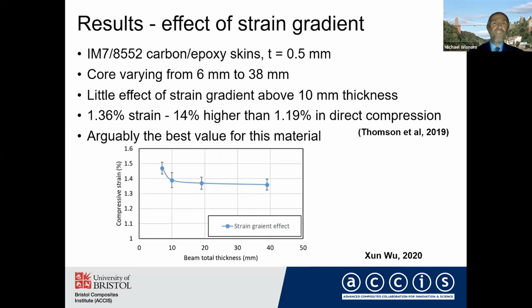What you see here for these 0.5 millimeter skins, with the core varying from 6 to 38 millimeters thick, is that at these very low levels the strain is increasing substantially. But once we get up past about 10 millimeters, there's not really very much effect. So these values here, I think, represent real compressive failure rather than an artificially high one that we get due to the suppression from the strain gradient when the specimens are thinner. That value there of 1.36% strain is about the highest value I've seen for compressive failure. The other highest one I've seen is 1.2% in direct compression, so it's significantly higher. I would say this is probably the best value for this material because we've eliminated the stress concentrations and we've also got a deep enough specimen to avoid a strain gradient effect. So I think this sort of testing gives us a real opportunity to understand a bit better what happens in compression failure and how it depends on various factors.